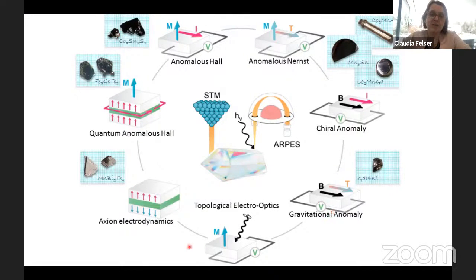And this is now really confusing, you see, so you can measure a lot. But most of the time, these measurements are transport measurements. So you simply use your PPMS, your physical property measurement system, which you buy from a company. You contact your crystal, apply a magnetic field and a temperature gradient, and measure the resistance. So I can already measure very, very many interesting properties. On this slide, you see some of the crystals, and all these crystals have topological magnetic properties. I already told you a little bit about manganese-3 tin, which is this non-collinear antiferromagnetic material for which we already did a lot of these measurements.